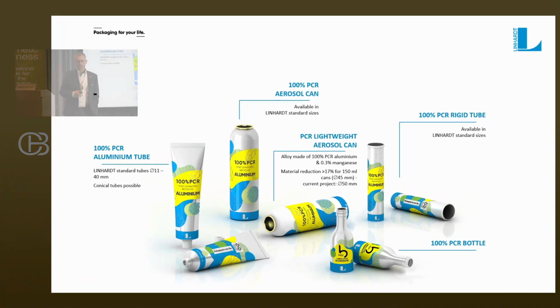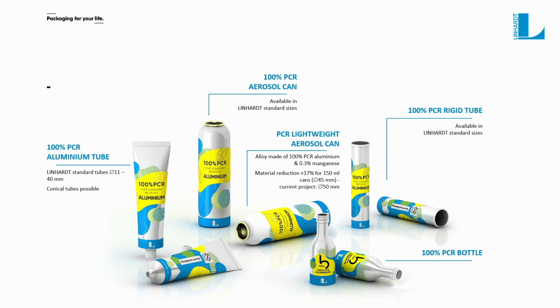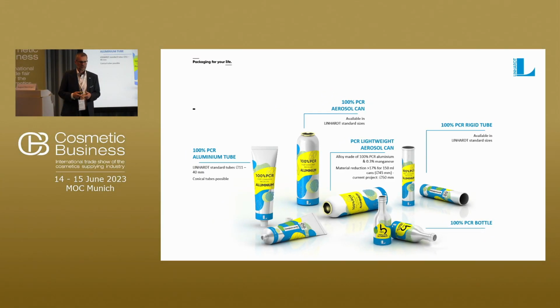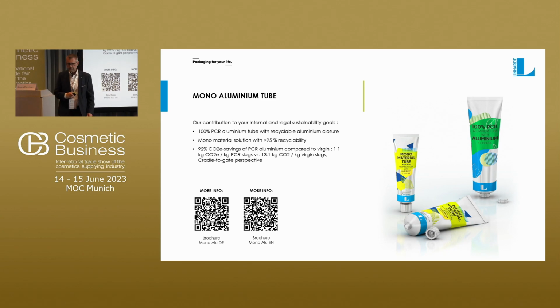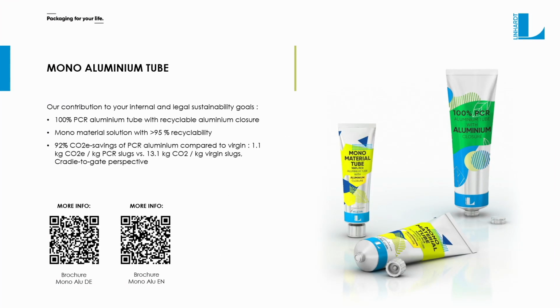So let me show you all our aluminum products at a glance here. We can offer everything with 100% PCR. We're currently developing a 100% aluminum tube with an aluminum closure. And let me tell you a little more about the aerosol cans. We can offer 100% PCR plus 0.3% manganese, which makes the material even harder, which allows us to further reduce the wall thickness, because an aerosol can is a pressurized can. This will allow for a further reduction in weight of approximately 17%, for 150 milliliter cans. And last but not least, the mono aluminum tube, which we're actually producing at large scale right now with 100% PCR.